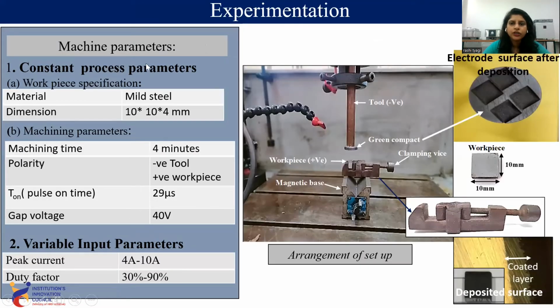Experimentation is performed as we have discussed for EDM. These are the constant input parameters that we are using. The workpiece material is mild steel, with these dimensions, machining time 4 minutes, polarity negative, positive. Pulse on time is 29 microseconds, the time for which current is allowed to go through the electrode. Gap voltage is 40 volts, peak current is varied from 4 ampere to 10 ampere, and duty factor 30 to 90 percent.